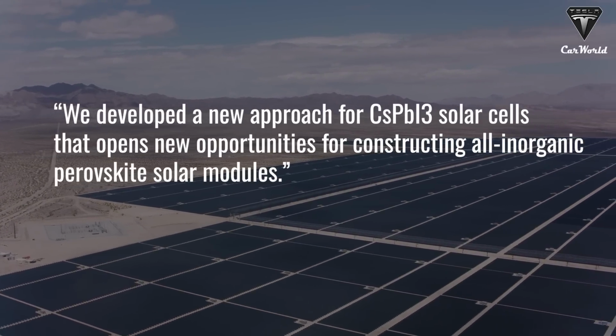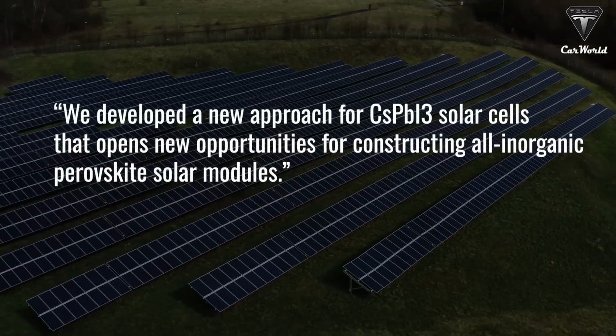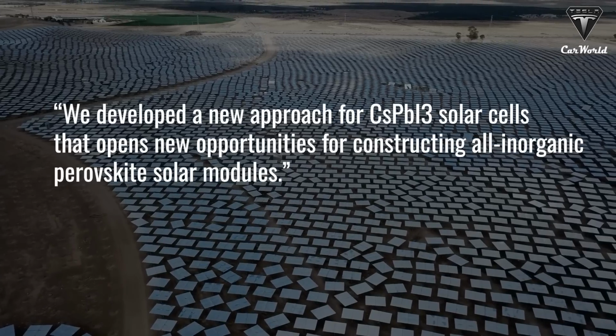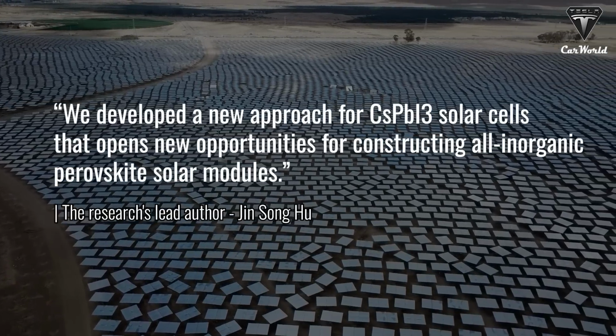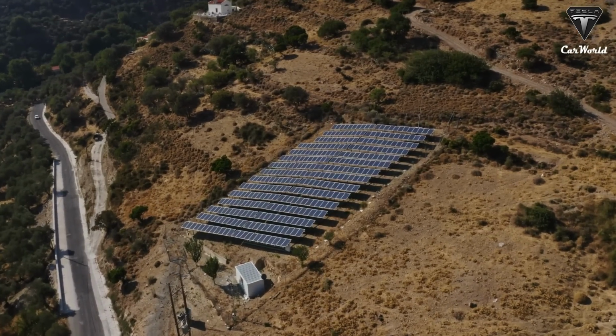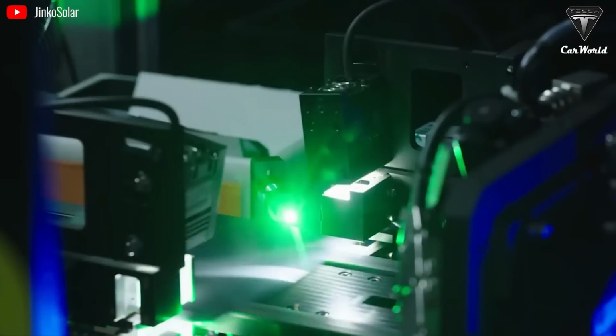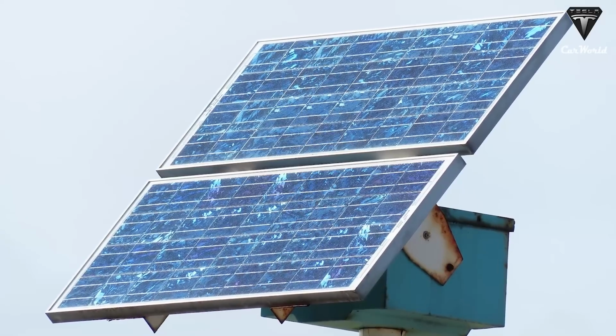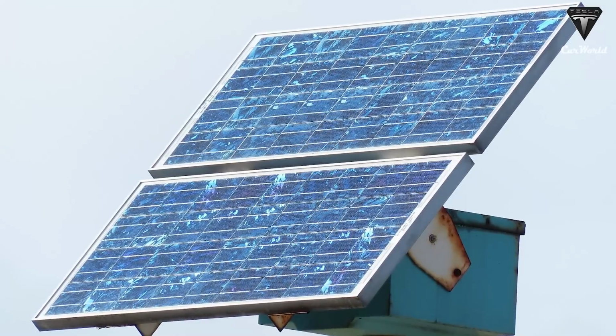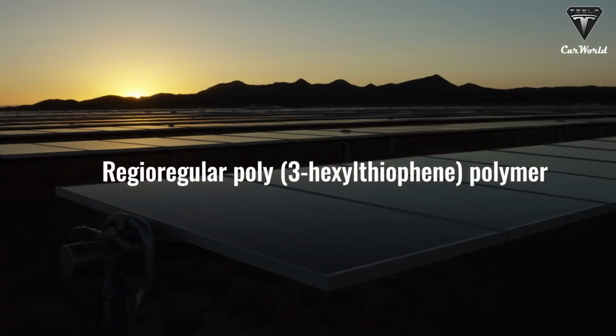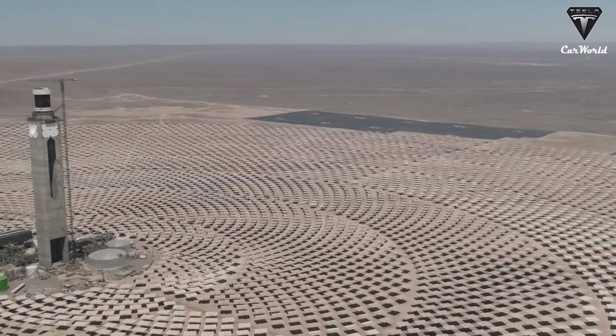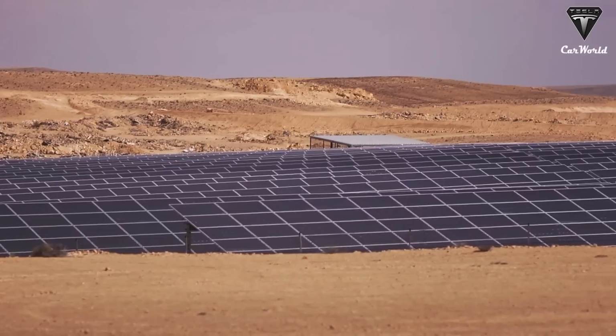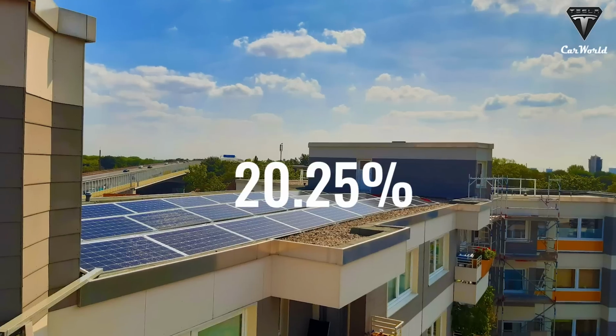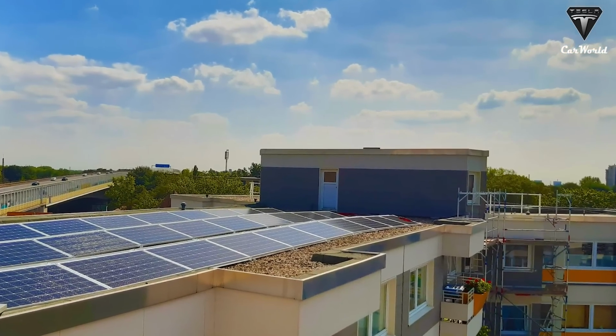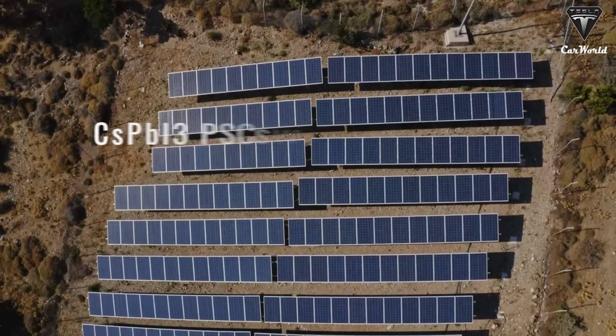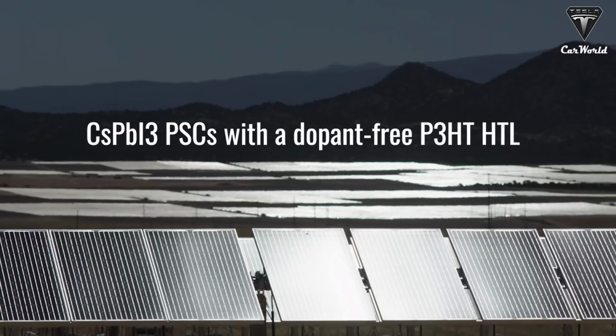We developed a new approach for CsPbI3 solar cells that opens new opportunities for constructing all-inorganic perovskite solar modules, the research's lead author, Jin-Song Hu, told PV Magazine. The group built the cell with a substrate made of fluorine-doped tin oxide, a titanium dioxide electron transfer layer, the CsPbI3 absorber, a hole transport layer relying on a regioregular poly(3-hexylthiophene) polymer, and a gold metal contact. Tested under standard illumination conditions, this device achieved a power conversion efficiency of 20.25%, which the scientists said is the highest efficiency reported on CsPbI3 cells with a dopant-free P3HT HTL.